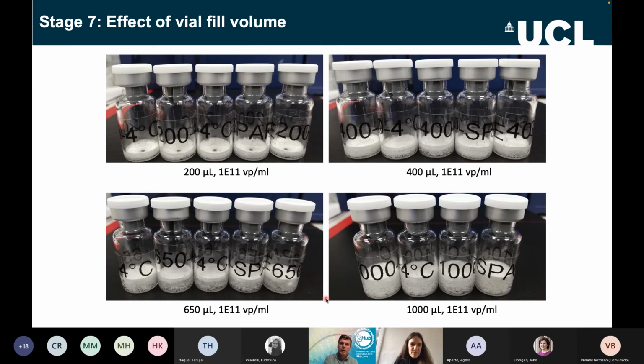Tricky to say. If you look at the GSK work, I think they did it on AAV. So there are similar issues that come up in terms of over-drying causing problems. So I think broadly the same kind of overall effects might happen, and then you have to optimize them in similar ways. But in the end, the actual formulations are different. I think there's enough difference between them that you'll end up with different formulations or different things added just to get it right. As ever with formulation, there are usually some general underlying trends, and then exceptions to the rule when you change your particle. That's what I would expect.